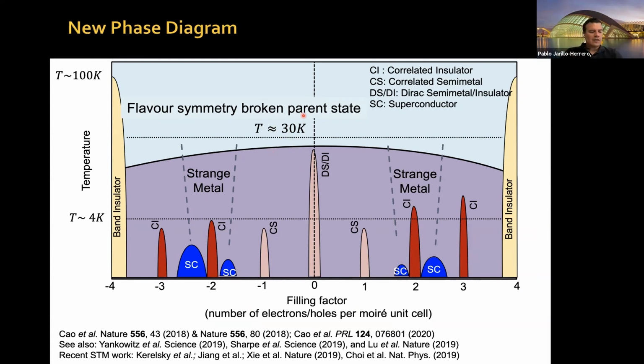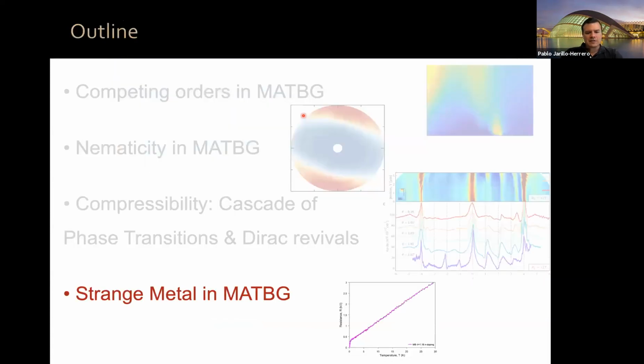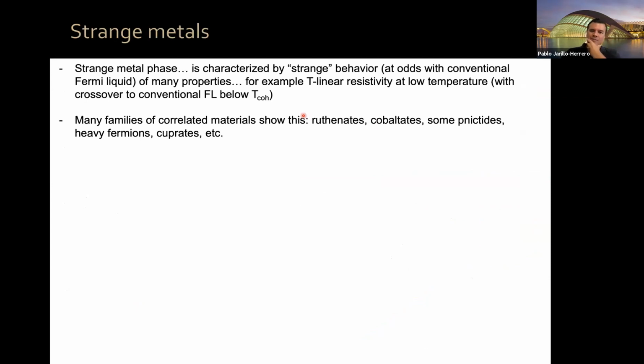So now, in the last 10-15 minutes, let me tell you about strange metal behavior in magic angle graphene. Now, what are strange metals? The strange metal phase is characterized by strange behavior, hence the name. It is behavior which is at odds with the conventional Fermi liquid behavior of many properties. And the one which is most emblematic is the linear in temperature resistivity, all the way from low temperatures to very high temperatures, but it's particularly striking that it goes all the way to very low temperatures. In some cases there is a crossover to conventional Fermi liquid behavior below some coherence temperature.